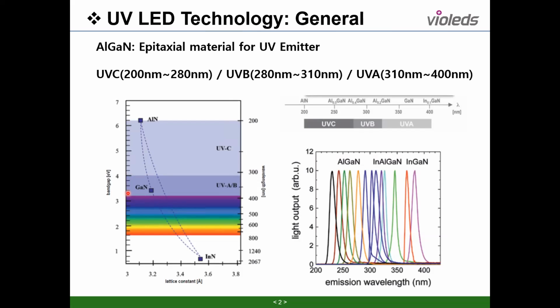So how much different? For the LEDs, the most efficient LED currently in technology is the UVA material. Like the 395 wavelength, the efficiency is much higher than the other wavelengths. It's even better than the white LED. In the case of wall plug efficiency, for the 395 it is more than 60%. And then when it goes lower, like the 365, it becomes like 40 to 50.